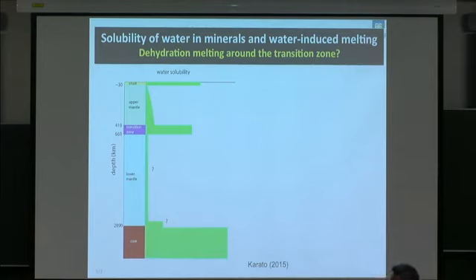What this means is that if the solid part has some solubility of water, then this water enhanced melting would not occur. So the condition at which water-enhanced melting occurs is very critically dependent upon the solubility of water in the solid component. If you plot the solubility of water in solid minerals as a function of depth, you find that there is a distinct peak at the transition zone. In the shallow upper mantle, solubility of water increases with depth to something like 0.1%. But in the transition zone, solubility is as high as 2 or 3 weight%, and then if you go to the lower mantle, solubility decreases.